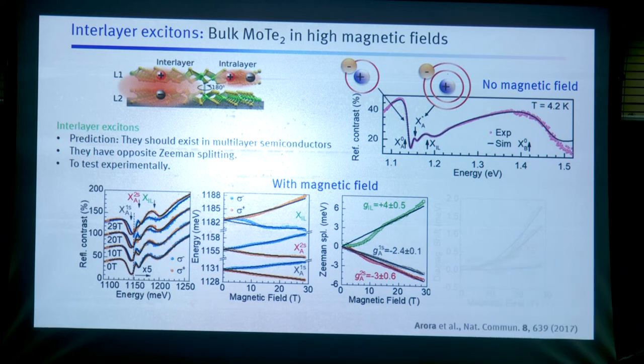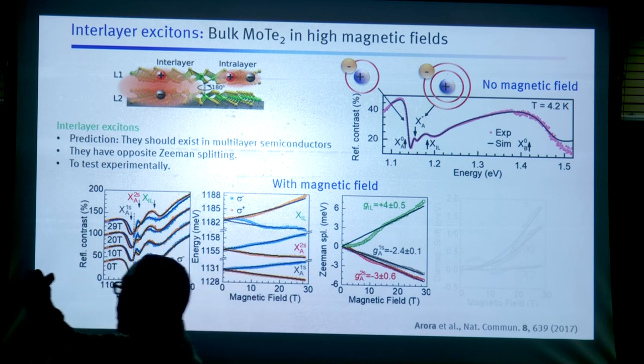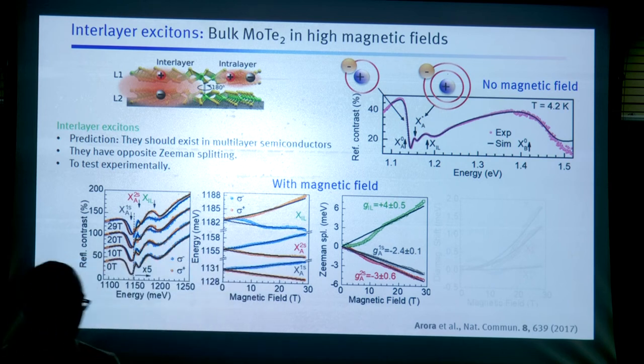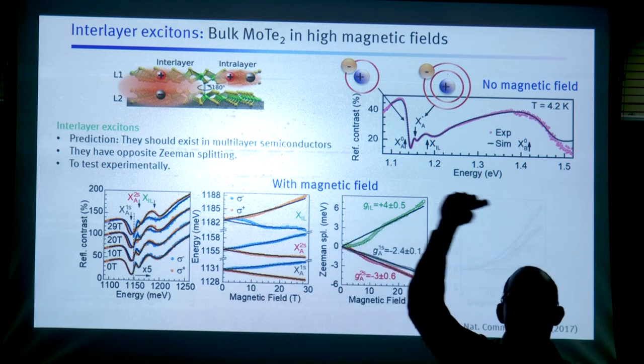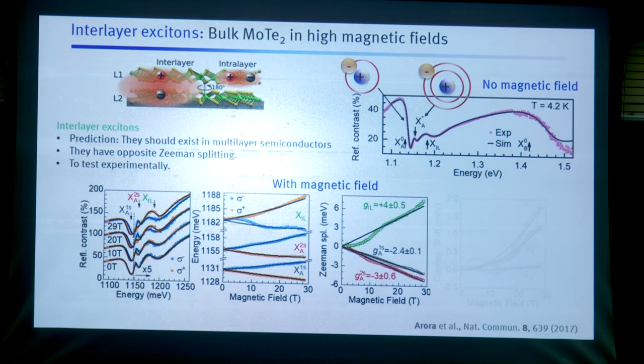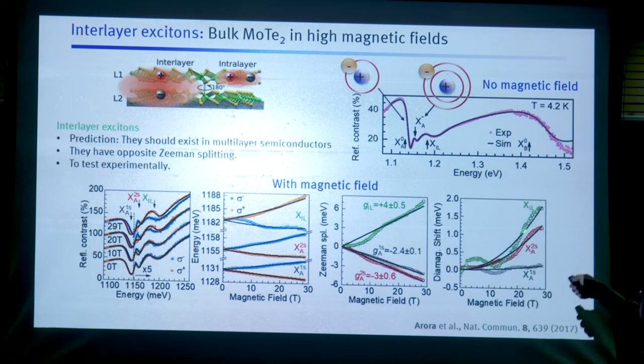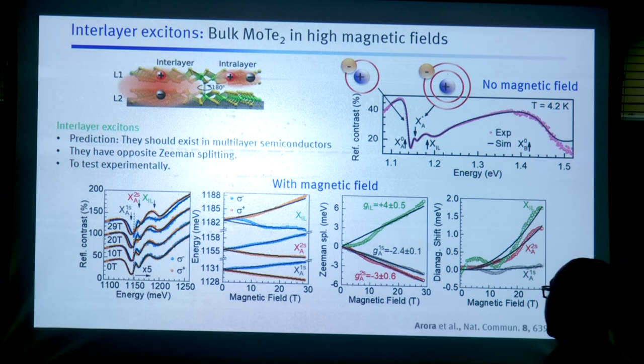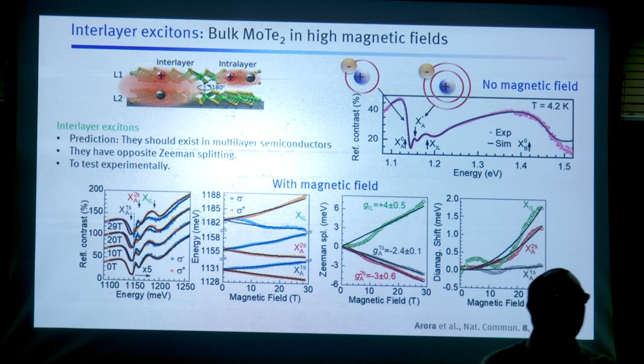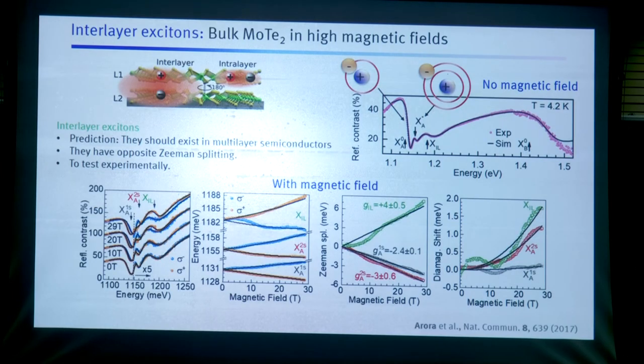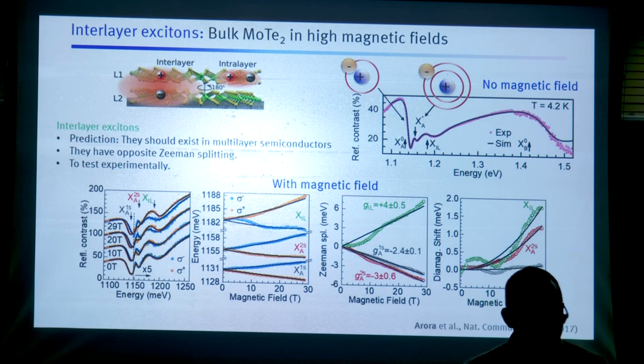The other thing is, if you have an interlayer exciton, this is a spatially separated exciton. So it is loosely bound compared to the other exciton, which is more strongly bound. When you have something loosely bound, with a large radius, it has a larger diamagnetic shift also. So we measured the diamagnetic shift and checked that this is a larger shift, and this is a smaller shift. So this is the normal exciton and the third is the interlayer exciton. Our colleagues also did theoretical calculations by solving the Bethe-Salpeter equation, which Mukul does as well. They found that there should be these excitations in the bulk of these materials, with a wave function mostly localized within the layer. And their calculations quite agreed with the energies which we found in our paper.